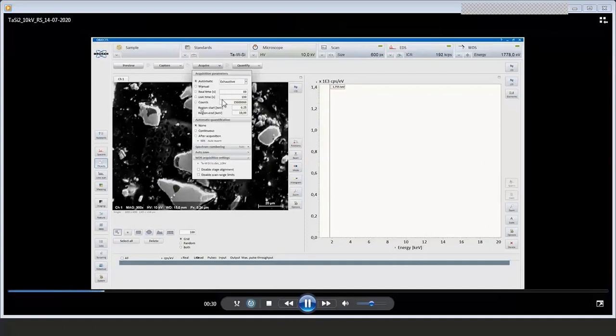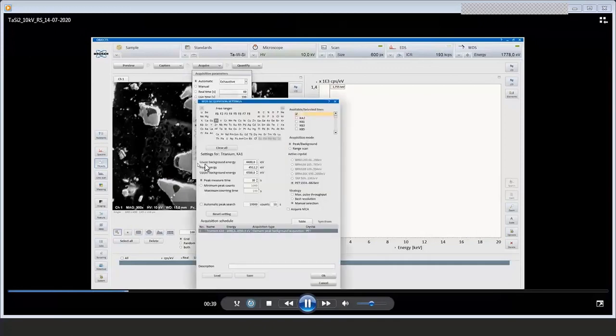We're setting now the acquisition conditions. Up here are the EDS conditions, and down there the WDS conditions. We open the menu. We are either selecting the elements or a free range here. So we are deciding for a free range. We are setting now the start energy and the ending energy for our range scan. We are setting then the step width for the range scan and the dwell time. And all this is summing up to the total time.